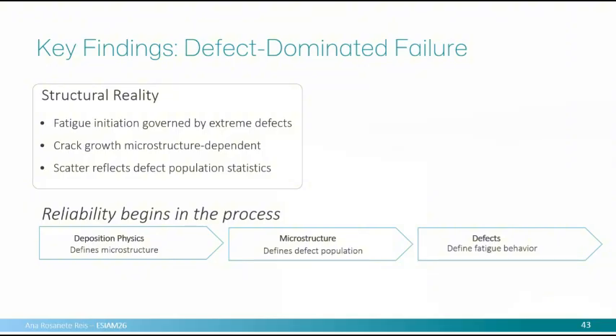So, summarizing the key findings in this layer, fatigue is governed by the biggest defect. Of course, it is microstructure dependent. Scatter is what we get, but my big conclusion is that reliability begins on the process, and that's my field. So when you are repairing, you need to look at the process, and the design of the repairing process is a constraint that you need to account for in order to predict your component life.